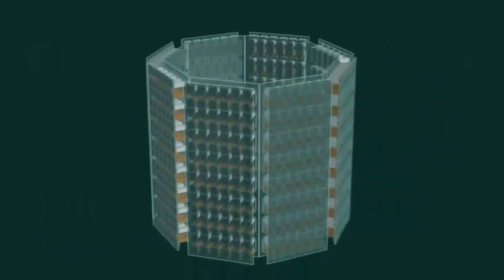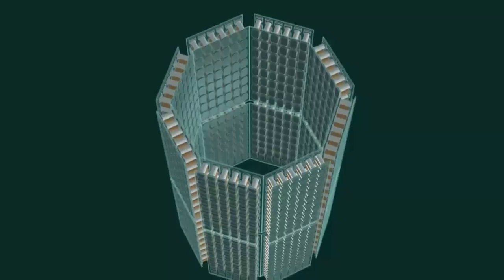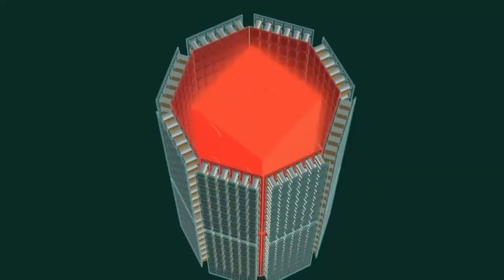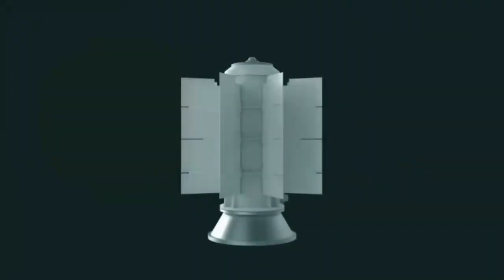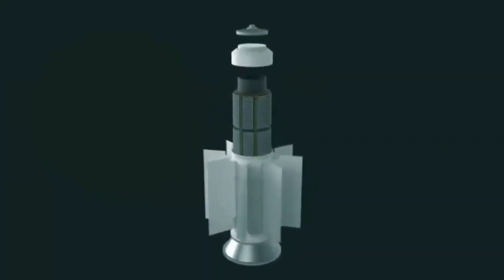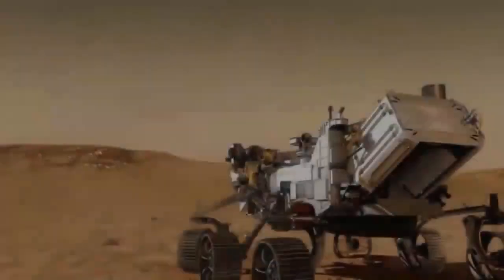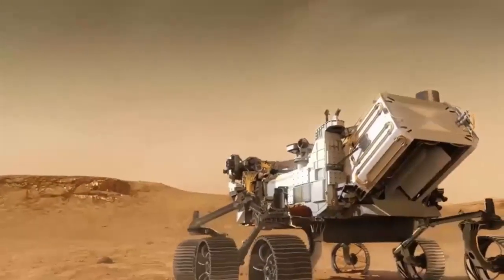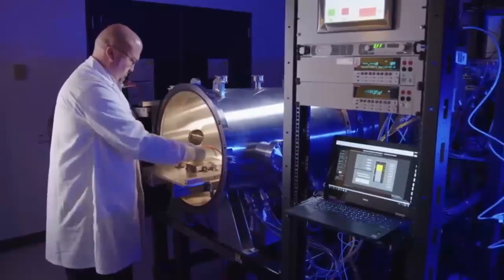In our Phase 1 study, we showed 8 watts of electrical power is possible from the 62.5 watt Pu-238 pellet from a general-purpose heat source, using a 0.28 eV bandgap TRC operating at 600 Kelvin. The necessary array includes 1,125 square centimeters of TRC emitters, or just over 50% of the surface area of a 6U CubeSat. With a mass of 622 grams, a mass-specific power of 12.7 W/kg is possible, over a 4.5x improvement from the heritage Multi-Mission Radioisotope Thermoelectric Generator, or MMRTG, was shown.